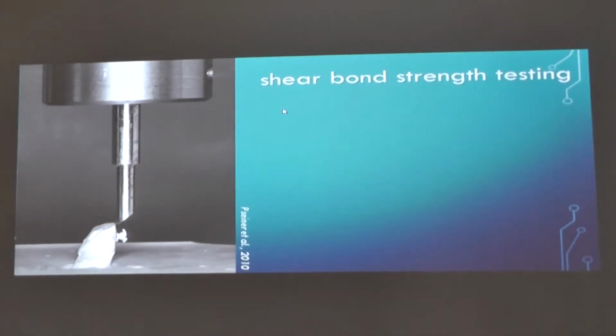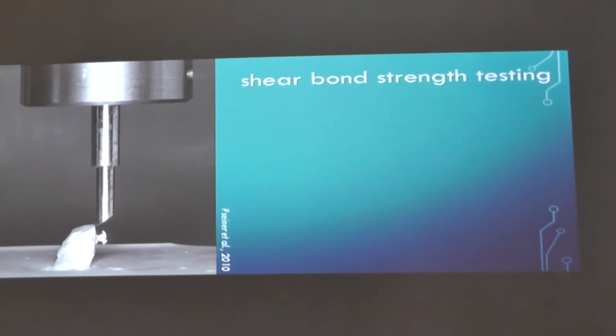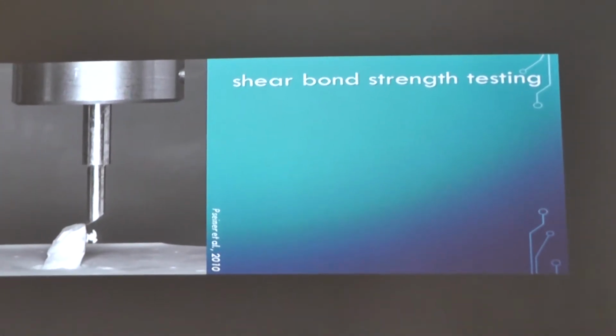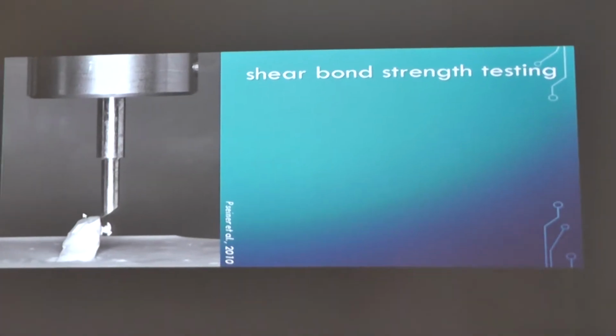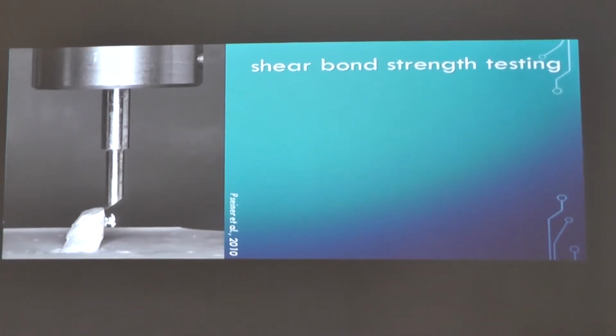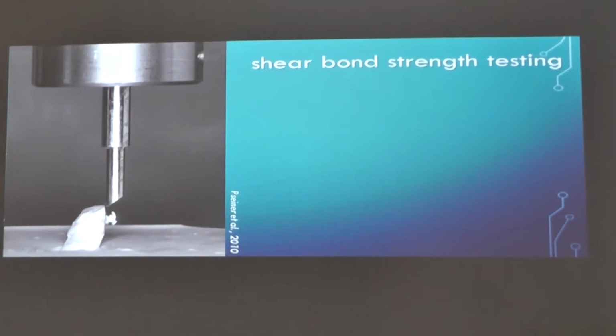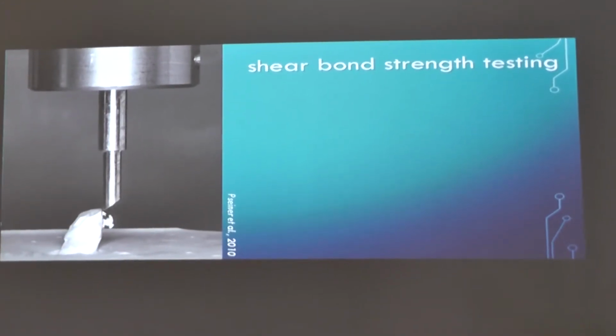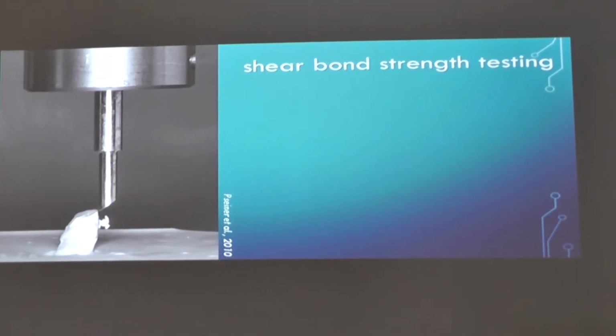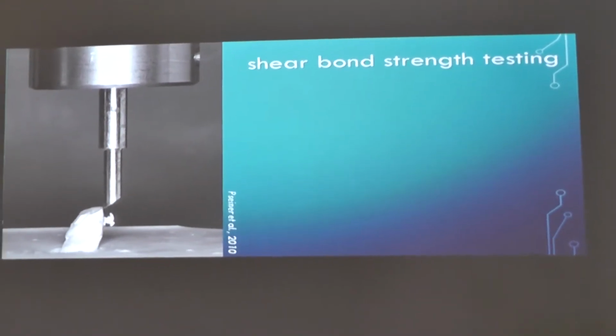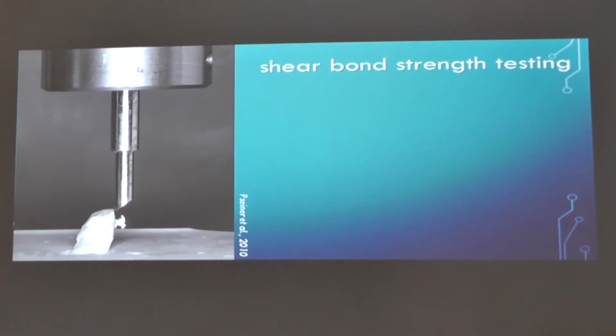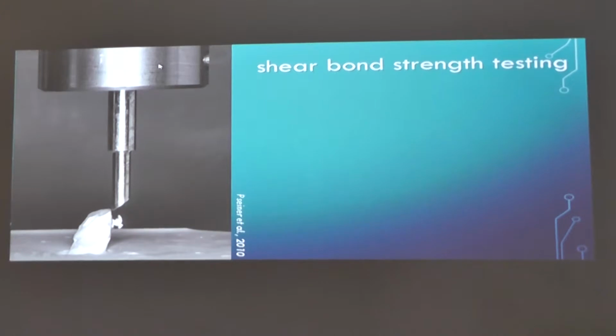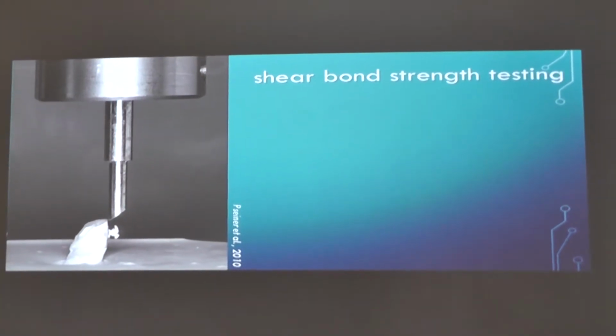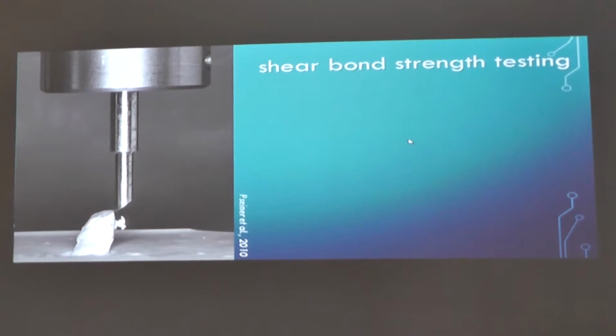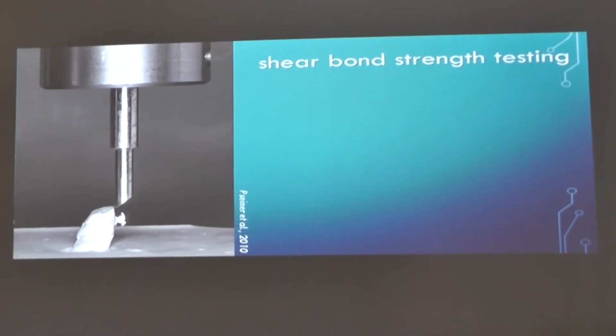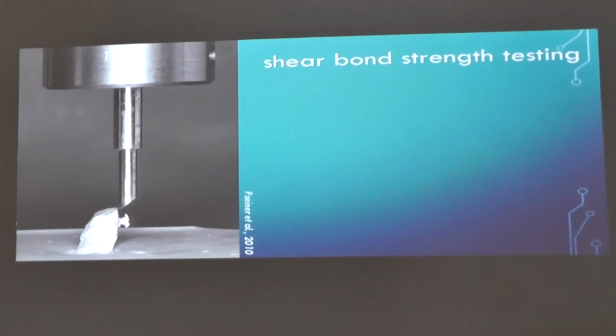And how do we test if the force is high enough? So this is the regular experimental procedure. It is called shear bond strength testing, and a tooth is prepared and a bracket is bonded to it, and then it has to be at a perfect angle in the testing machine, so when this piece of the instrument presses, it records the force at which failure occurred. So it resists, and then at one moment it fails. And also clinically, so this has a lot of drawbacks, this type of investigation that I won't go into now.